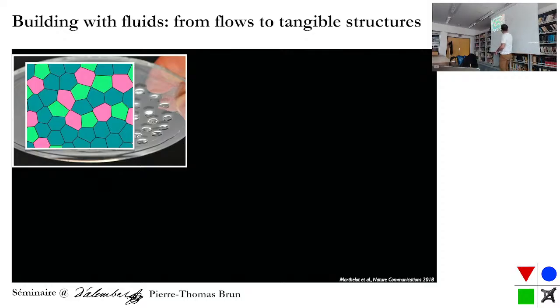After the droplets are formed, they can still talk to each other. They flow, they can merge, they can drip. So there are all kinds of complicated things that happen. But what we discovered with Joel is basically that if we were to make little holes into the plates in which we're making these coatings, and by holes, I mean we actually laser impulse on the acrylic, so we make little dents, and we make these dents at about the size that we expect from the instability, right? So everything is in the about, right?